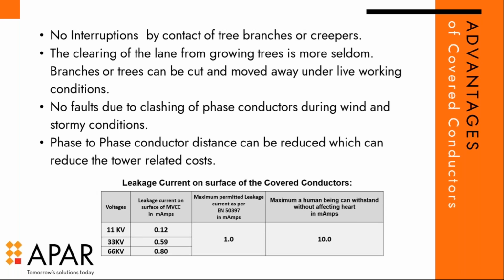The leakage of the current, as I told you, should be less than 1 milliamp. When we tested the technology, at 11 kV it comes out to be 0.12 milliamps, at 33 kV 0.59 milliamps, and at 66 kV it is 0.80 milliamps. So the leakage is well within the limits, and the human heart can sustain up to 10 milliamps. So it is a completely safe technology for human beings as well as for wildlife.